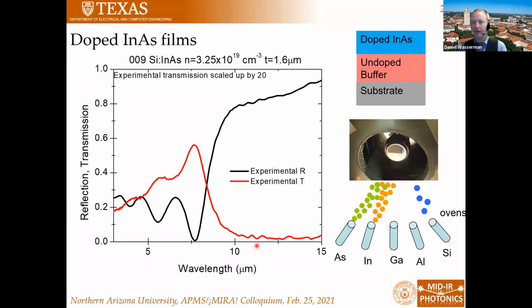So this is not the best sample we've ever grown. This is in fact one of the very first samples we've ever grown. You can see 009, so that's one of our first 10 samples that we grew at Illinois, where we just doped the heck out of a layer of indium arsenide on top of an undoped layer. What you can see if you look at the reflection is these oscillations, right? Those oscillations are the Fabry-Perot oscillations in this doped indium arsenide, at the interface with this undoped barrier.